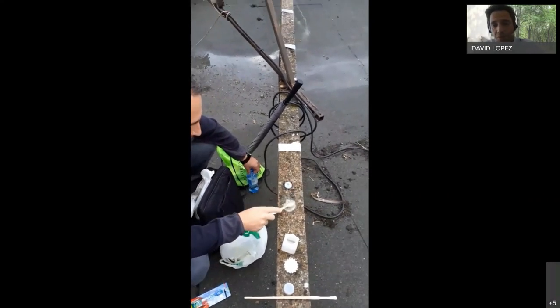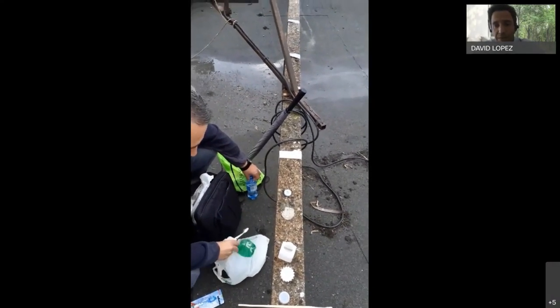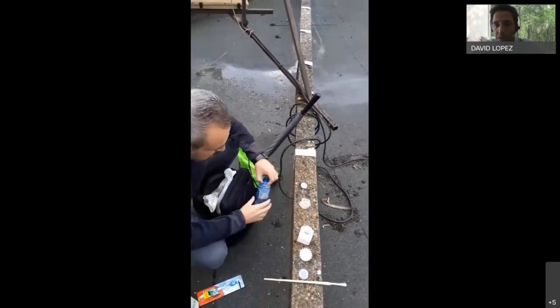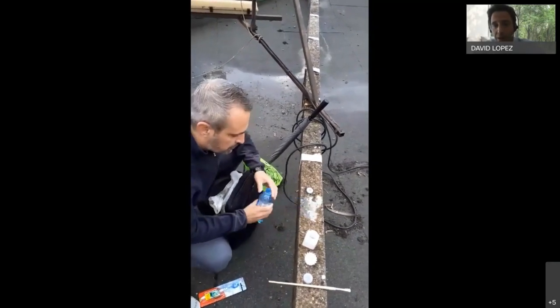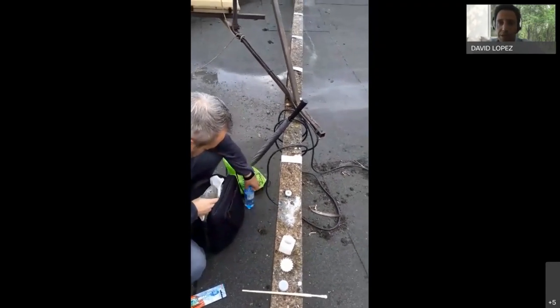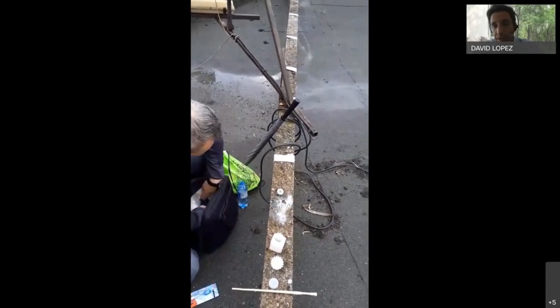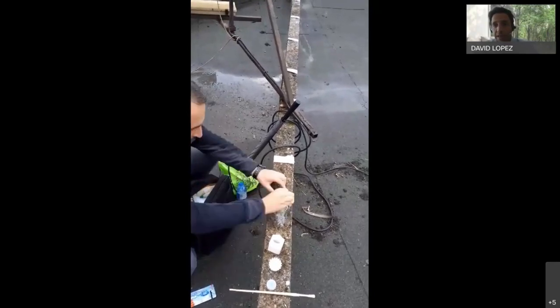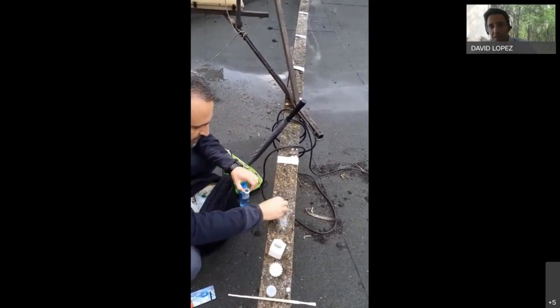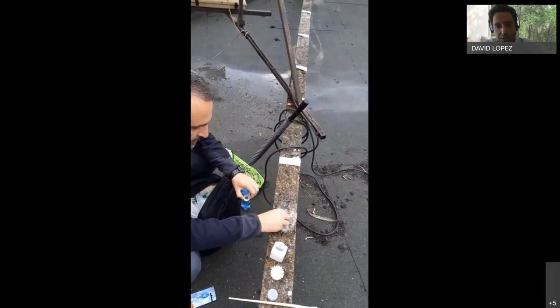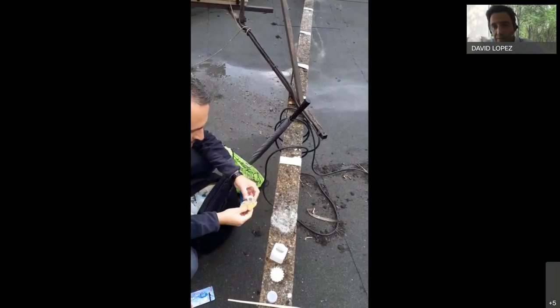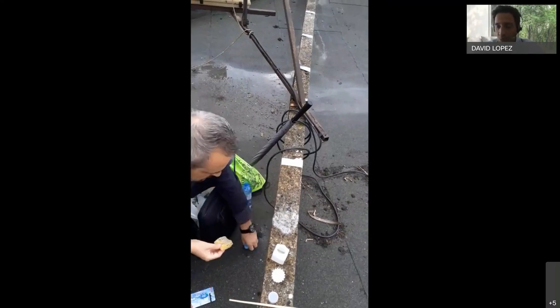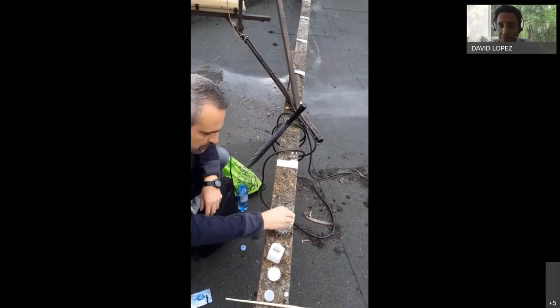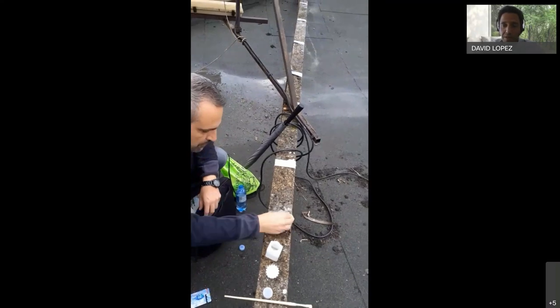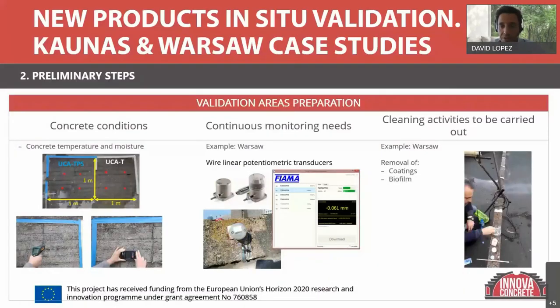And finally, we have an example of what we need to clean, the surfaces in certain occasions. We remove biofilms, like in this case that you see in the video, and we also need to remove, for example, coatings, mainly for applying products that require impregnation, which are mainly consolidants, superhydrophobic products, and the corrosion inhibitor products. Why is this? Because if you have a biofilm or coating, they are in a way covering the pores, and then if the pores are covered, the product cannot go through the surface and act protecting the concrete.